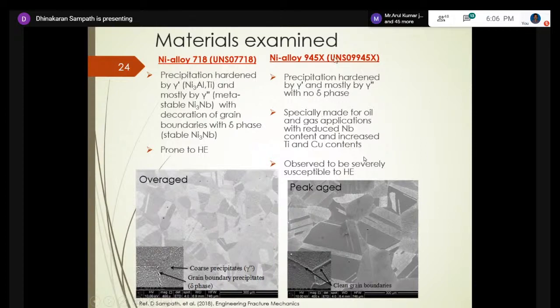And we have this new alloy, which is again precipitation hardened using gamma prime and gamma double prime, but no delta phase. They found that delta phase is detrimental, so they tried to design it in a way that it doesn't have delta phase. That's what they changed. They reduced niobium, which is what forms delta phase. And this alloy microstructure is a peak age.